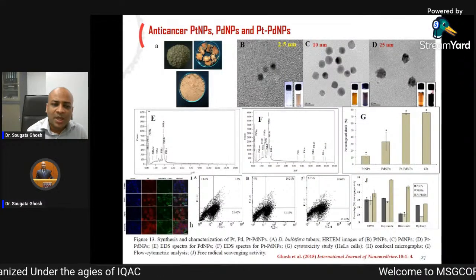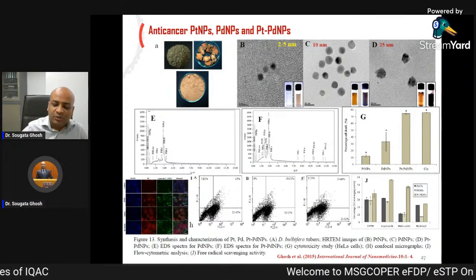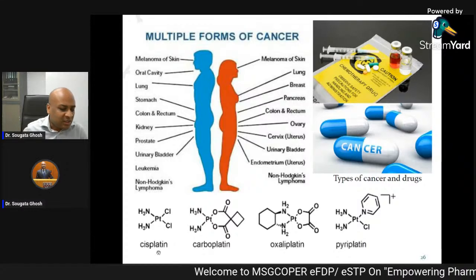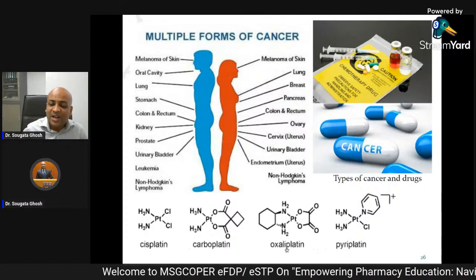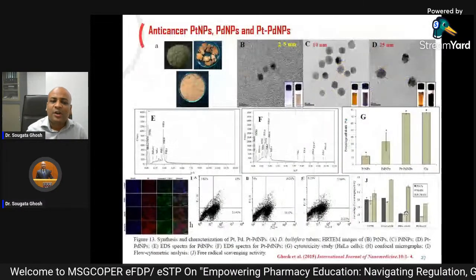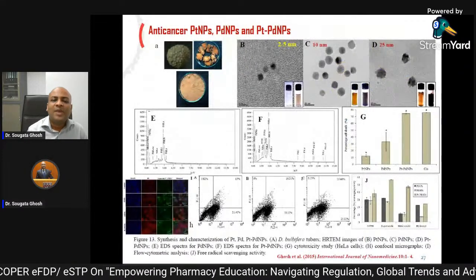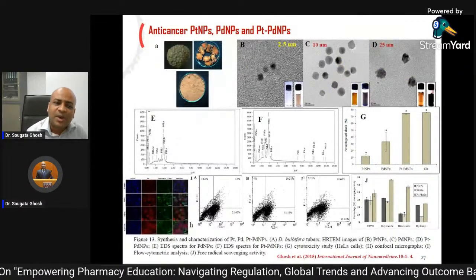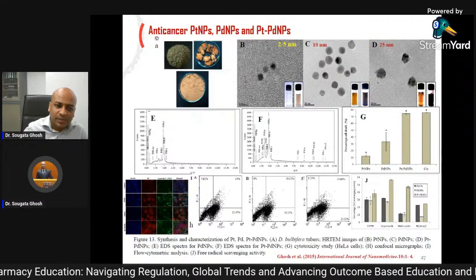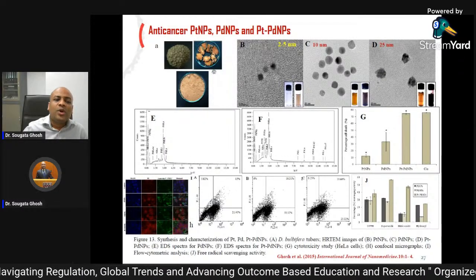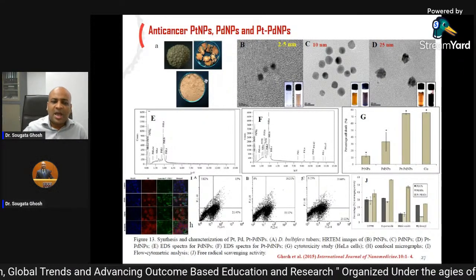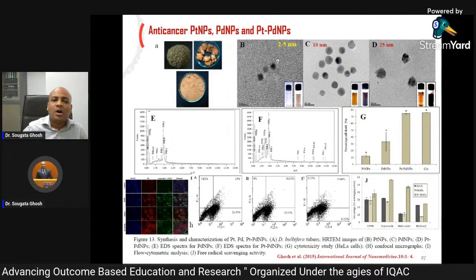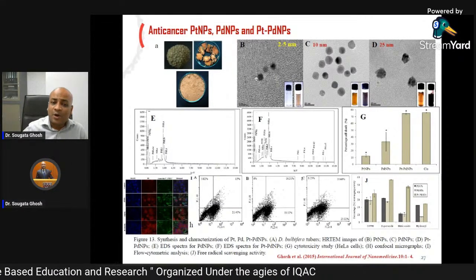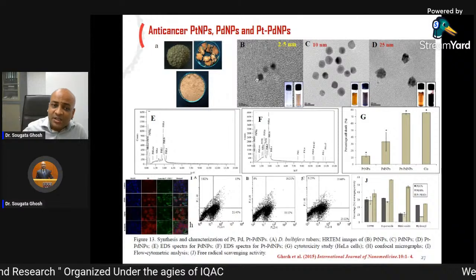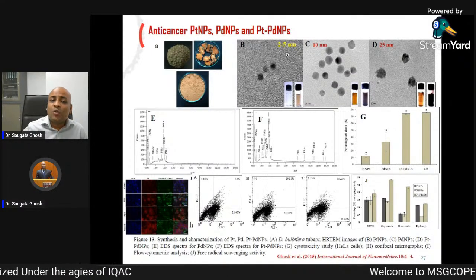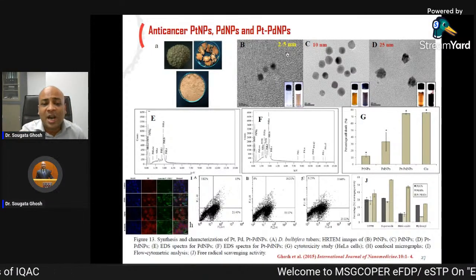That's why we thought, can we develop these platinum-based drugs? You can see these drugs are platinum based: cisplatin, carboplatin, oxaliplatin. So we thought, can we develop platinum nanoparticles, platinum-based drugs, from this plant? So we used the same Dioscorea plant and we took the extract. And after using this extract, we saw that it could produce platinum nanoparticles. What is the size? Just 2 to 5 nanometers, a very, very, very small nanoparticle.